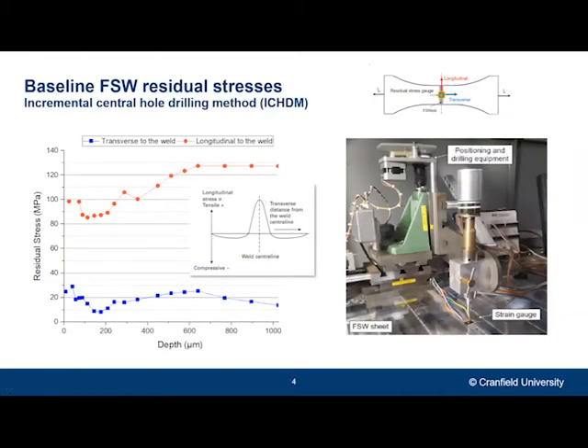As I explained in the previous slides, there is technically no fusion in this process. However, the heat input is high enough to leave the material with substantial residual stresses. So I measured these strains and calculated the stresses in my fatigue samples, which you can see here at the top, using what's called the incremental central hole drilling method, by placing a rosette gauge in the center of the weld. As you can observe, the stresses along the weld line, which are the red dots, are tensile in nature and close to 100 megapascal.